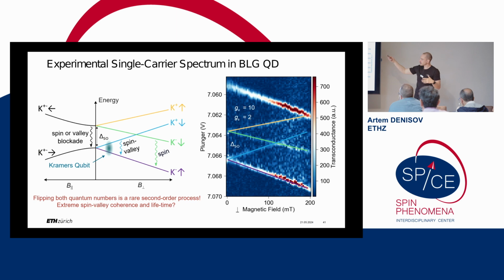And now we can talk about the spectrum. It's actually very interesting because if you want to make a qubit out of it, so we're talking about a ground state and an excited state, just as a function of magnetic field, you can go between different blockade regimes. So at a high magnetic field, you start with just the two spin blocked states, this green and this purple state. They're just spin blocked, K minus down and K minus up. However, if you reduce your magnetic field, so you go before the crossing, this blue state and this purple state, they are spin-valley blocked. So these are two states from the Kramers pair. So for historical reasons, if you want to make a qubit out of these two states, it's called the Kramers qubit.